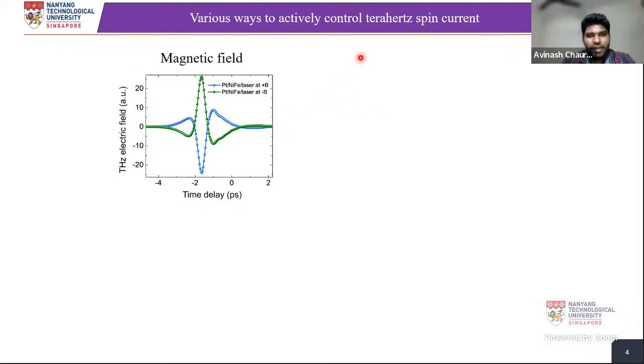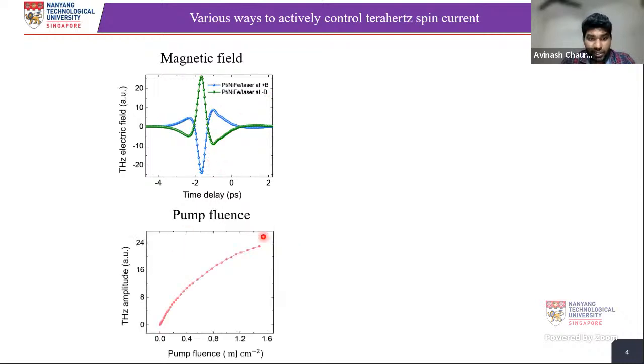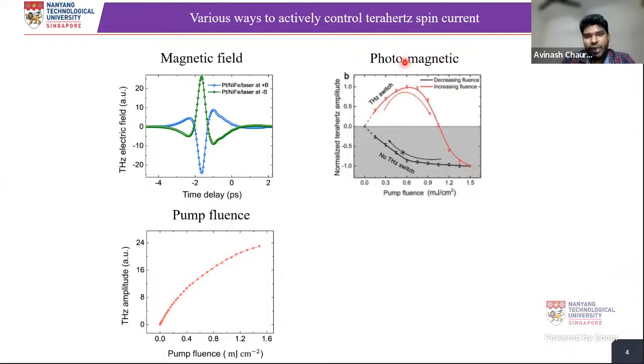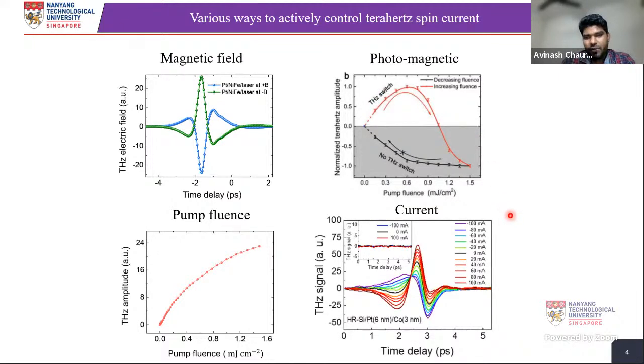There are various ways to actively control this terahertz amplitude. By applying a magnetic field, we can control the terahertz amplitude as well as the pulse, and also by increasing the pump fluence of the laser, we can control the terahertz amplitude. But we cannot control the phase of the terahertz just by increasing the fluence. By combining the photo and magnetic field effects, there is a report that we can switch the phase of the terahertz pulse. So these are some active ways, and there is also an electrical way by using current.